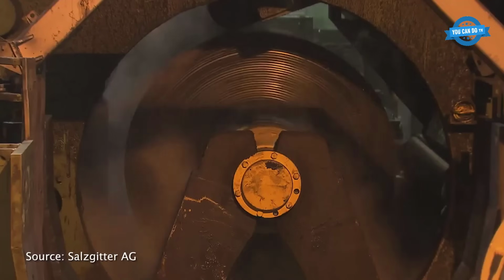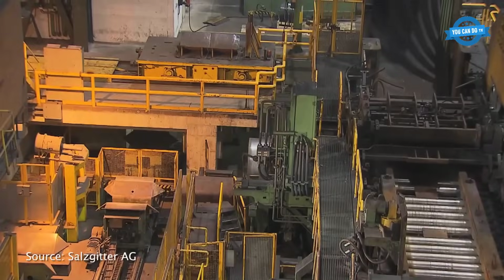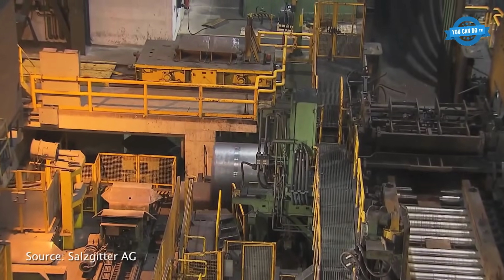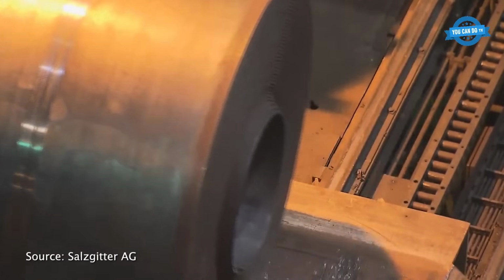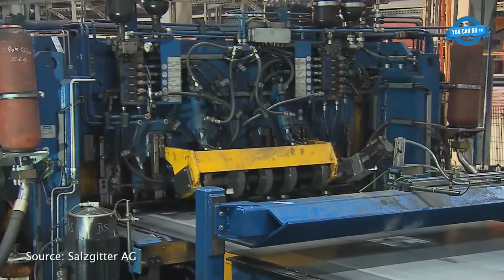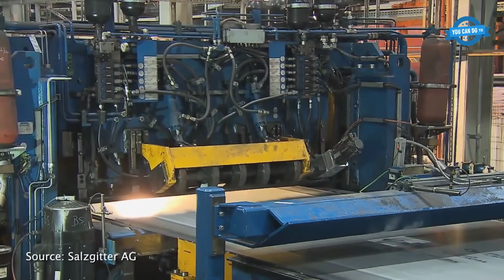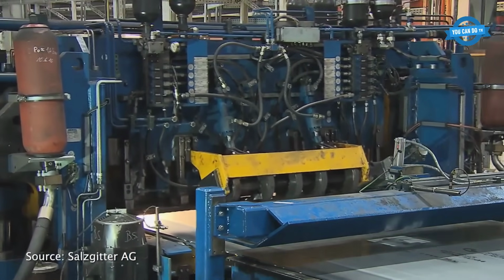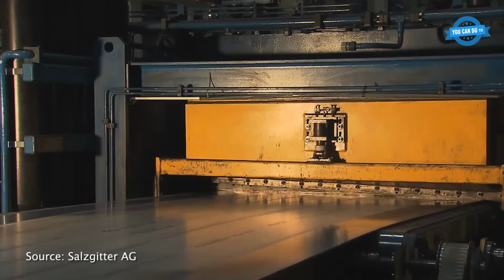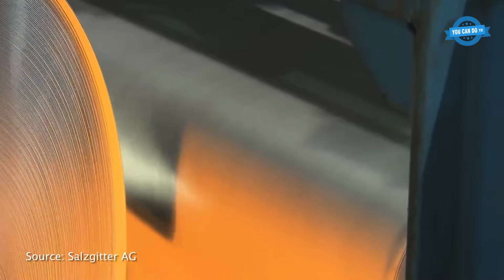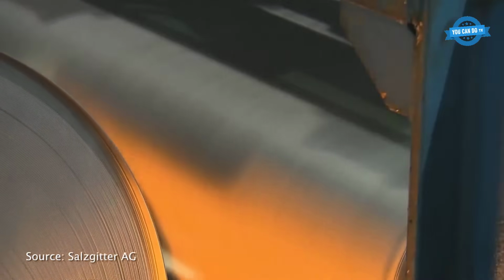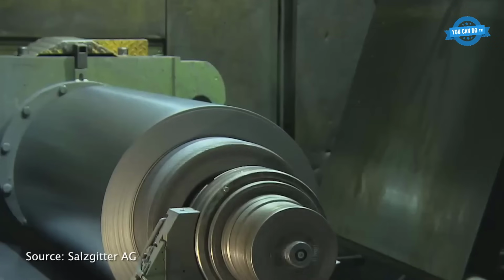The pig iron is then transferred via torpedo ladles to a steelworks, where it's poured into converters alongside scrap. Using the LD process, pure oxygen refines the melt, removing impurities and reaching temperatures around 1,700 degrees Celsius in about 40 minutes, yielding raw steel. Alloying elements like manganese or chromium are added to tailor the steel's properties.